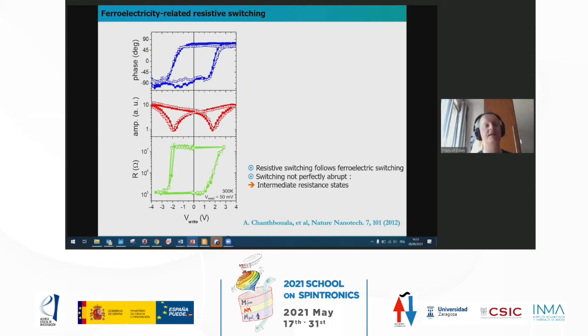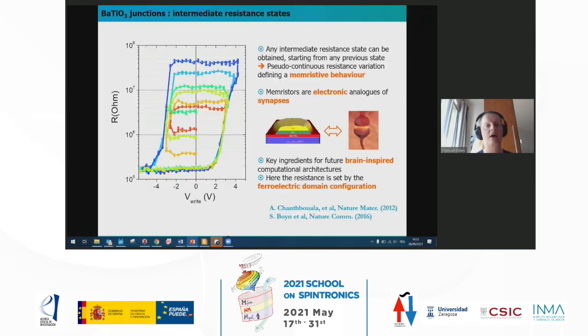We show that they can be relatively fast. They work at low dimensions. And also, this probably echoes a bit some of the things that Julie discussed before my talk. We showed that in these tunnel junctions, you can stabilize any intermediate resistance state. You don't have access to just these two extreme states. You basically have access to a pseudo continuum of states in between, depending on how intense the voltage you apply is, but also on how long you apply it for. And this defines a device called a memristor, which are electronic analogs of the synapses in our brains. And so, collaborating with Julie, we implemented a number of operations, including the demonstration of spike timing-dependent plasticity with these junctions. And we also showed that the resistance level was here determined by the ferroelectric domain configuration.